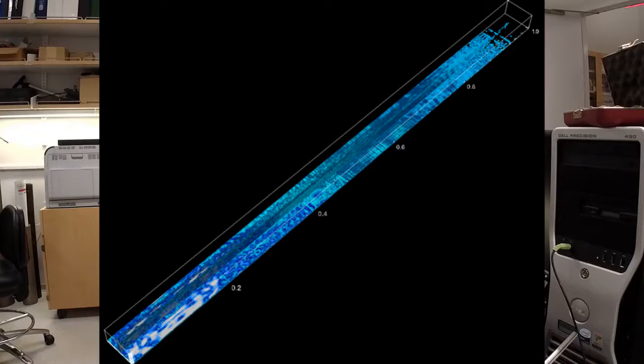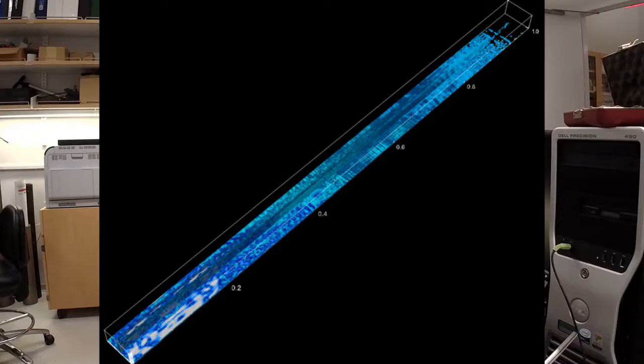That movie is cool. And also, it's not just cool. These simulations allowed us to figure out a quirky thing that was happening in our analysis method. We were trying to pick off the arrival times accurately to tell changes in arrival time due to structural flaws. We had always been able to, in simpler things like plates, pick off that first arriving mode rather accurately. What we were finding is that for these T-stiffeners, we weren't able to pick off that first arriving mode, but we were able to pick off one of the later arriving modes. Looking at the simulation results in detail, we found out, just dumb luck. In our case, the particular size of the web relative to the frequencies that we were using meant that where we were trying to pick off that arrival time, the signal bouncing around inside this three-dimensional structure was sort of canceling itself out for that first arriving mode, and that's why our algorithms were automatically tracking the second arriving mode.